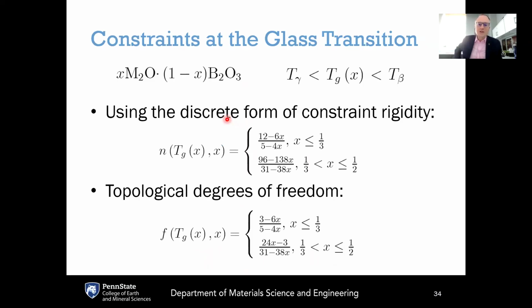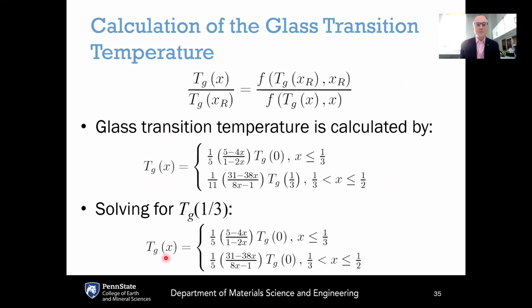Now, putting this all together into temperature-dependent constraint theory, we use the formulas from Gupta's random pair model, use all of the rigid constraints, the rigid alpha constraints and the rigid beta constraints, and that gives us a formula for the number of rigid constraints per atom in the glass transition region, which is shown here. And then 3 minus that gives us the topological degrees of freedom, because if you start off with 3 degrees of freedom, every time you have a rigid constraint, it takes away one of those degrees of freedom. So 3 minus n gives us f, the topological degrees of freedom.